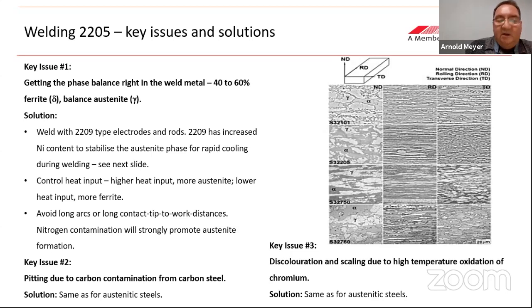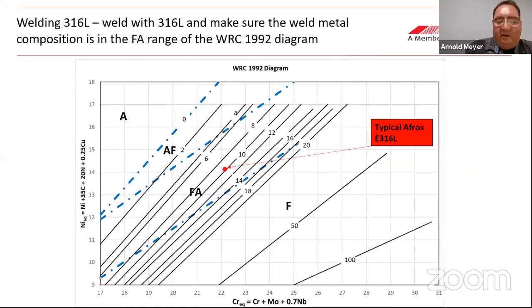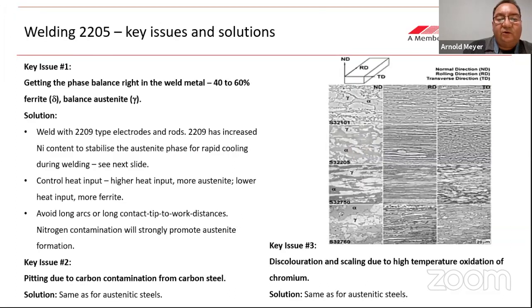and your phase balance will not be right. To explain this, let's go back to the diagram, and you look at the nickel equivalent there. Your nickel equivalent are the elements that will stabilize austenite. You can see that nitrogen is 20 times as effective as an austenite stabilizer than nickel. So with nitrogen, you don't want your duplex stainless steel weld metal to be contaminated.